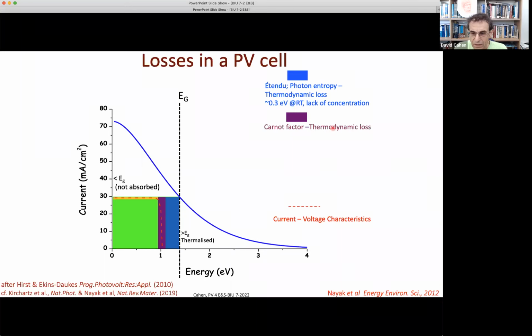Then there is a Carnot factor. Even though this is a system that's really in steady state and not in thermodynamic equilibrium, Sadi Carnot still reigns, and I lose a little bit. Because I can look at the system as the sun at 5,800 Kelvin, and we luckily are only at 300 Kelvin. Now you can be a smart ass and say, since these are thermodynamic losses, I go to 0 Kelvin and then I get a very, very efficient solar cell. There's even a paper recently in a very respectable, supposedly, journal, which says that they made a cell and they cooled it as if no one had done it before, and it became more efficient, and therefore it's very good for space. They naturally forgot that the main problem for solar cells in space is thermal management, and they only work when they face the sun. Otherwise, they're not converting anything.